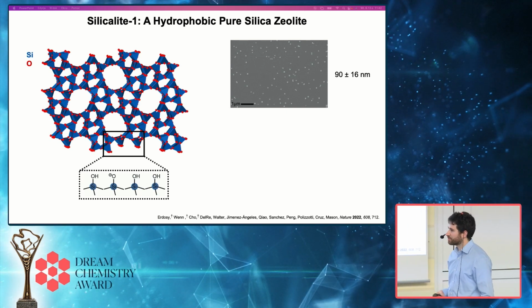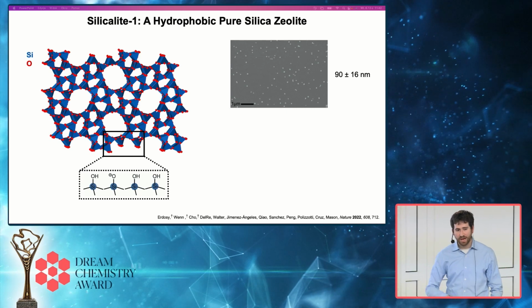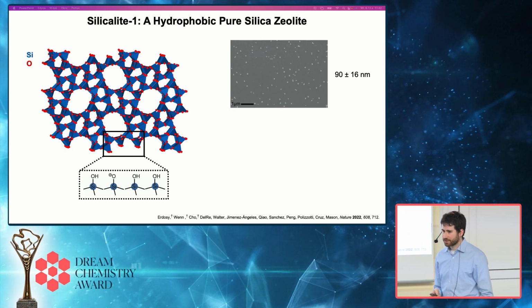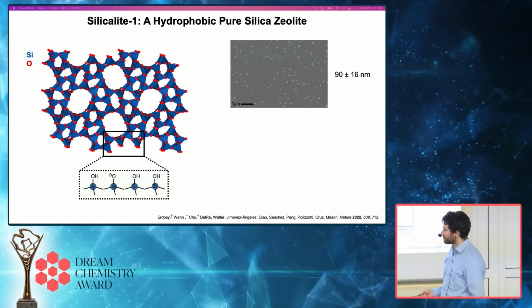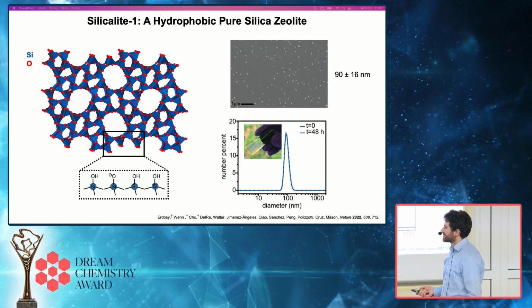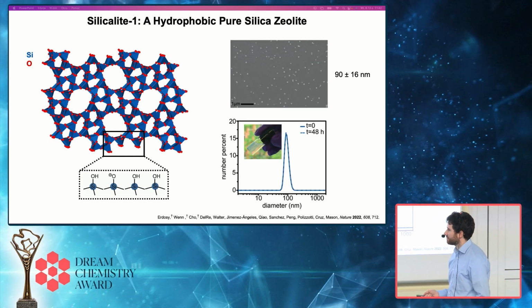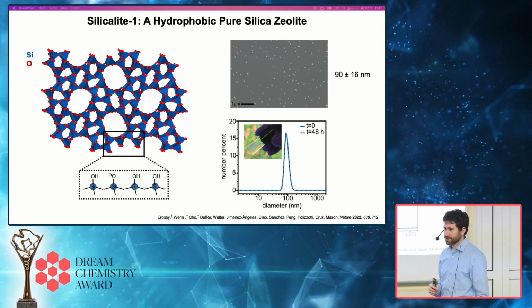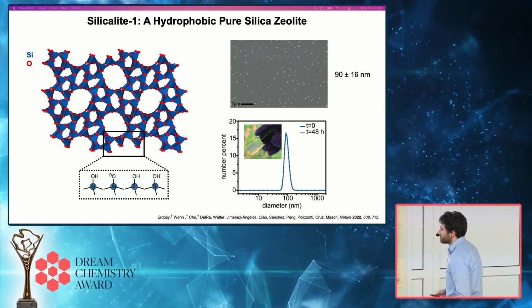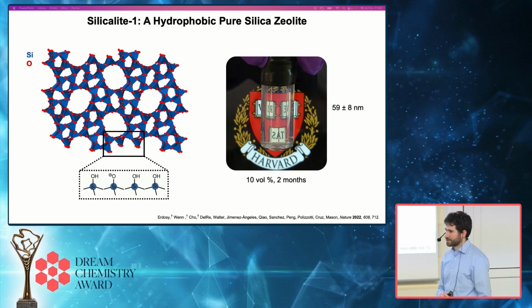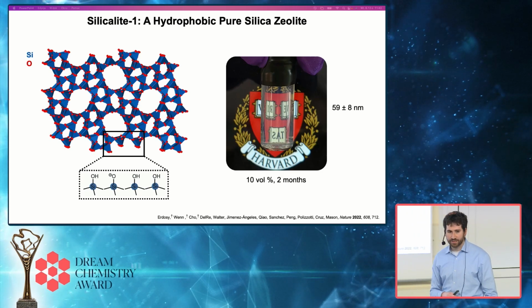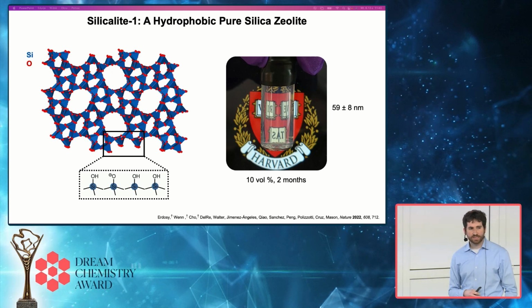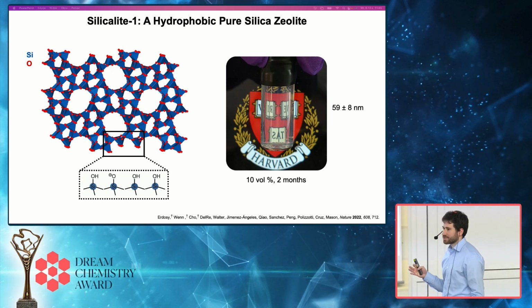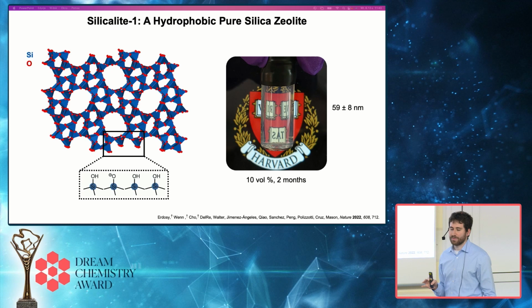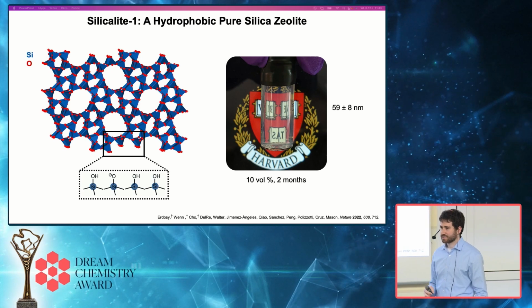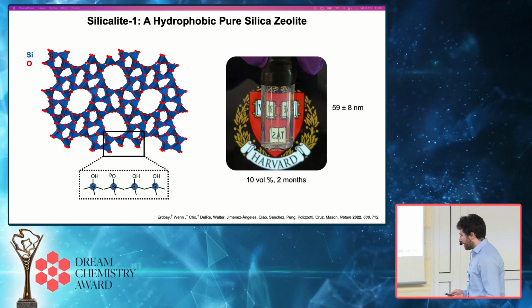This is one example here, but we can make anywhere from about 50 nanometers to as large as 300 or 400 nanometer size nanoparticles that after you spend some time purifying them and figuring out how to activate them can form really nice colloidally stable dispersions in water. These can be really, really stable dispersions where we don't observe any signs of settling or aggregation over periods as long now as like 6 to 8 months. These are translucent solutions that at moderate concentrations and small particle sizes really look like water.